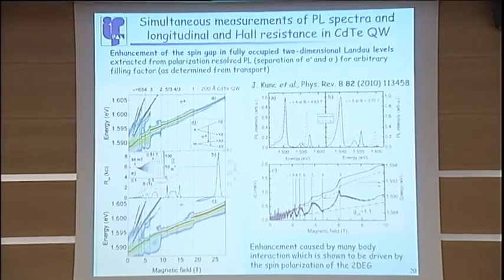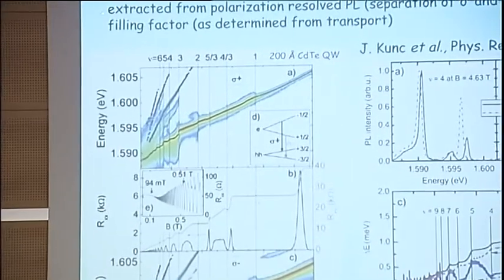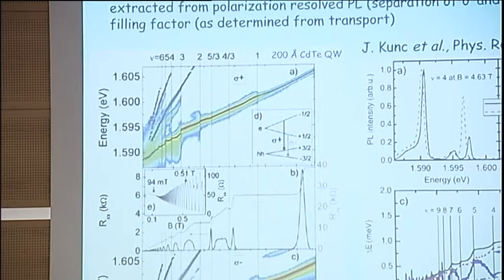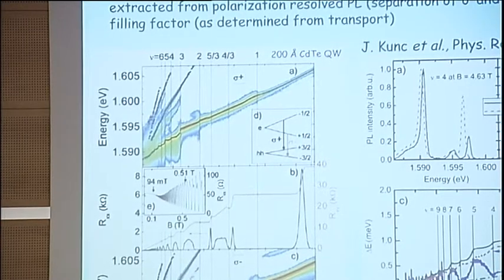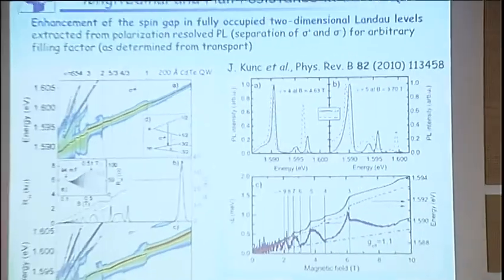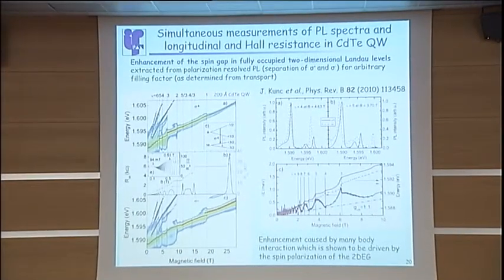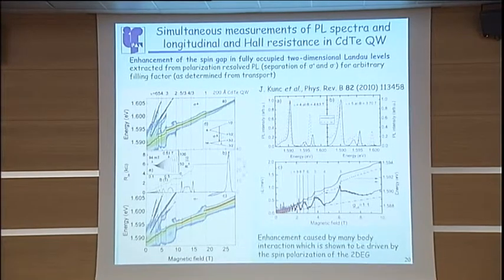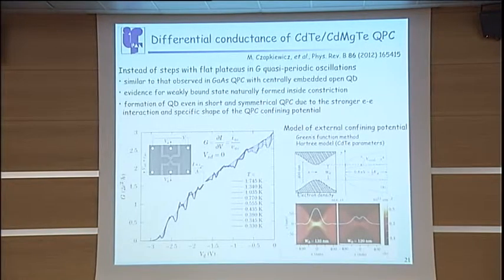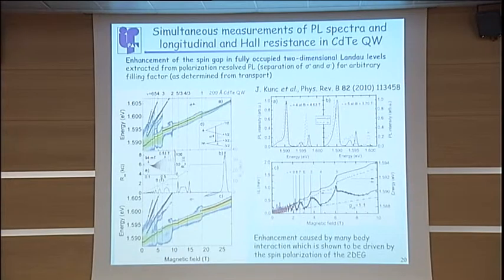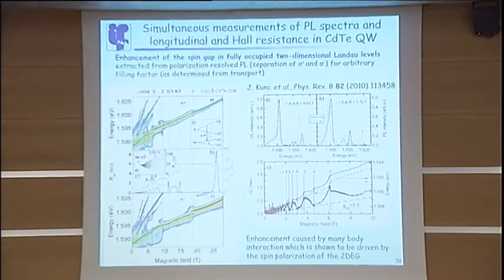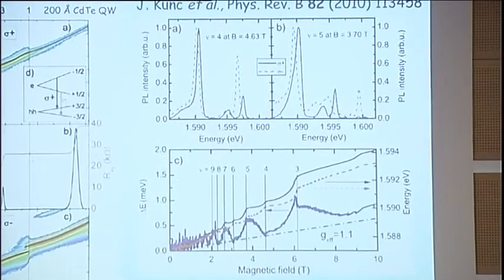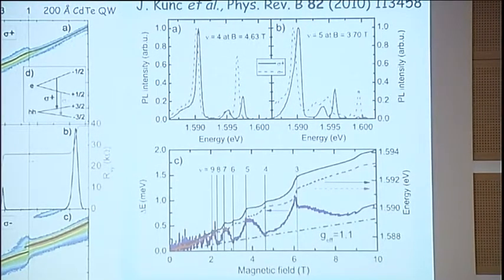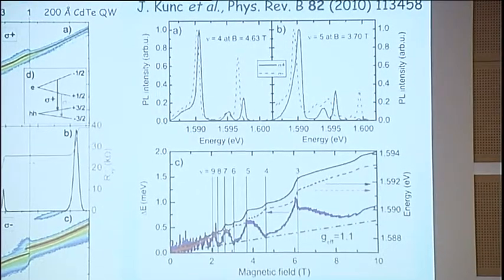Our colleagues from Grenoble have shown the enhancement of the spin gap in the fully occupied two-dimensional Landau level, which was extracted from polarization-dependent photoluminescence, and for an arbitrary filling factor, which has been precisely determined by transport measurements. And they have explained this enhancement through many-body interaction that has been driven by spin polarization of the two-dimensional electron gas. And you can see this enhancement here: whenever the filling factor becomes odd, you have a large enhancement of the spin splitting.